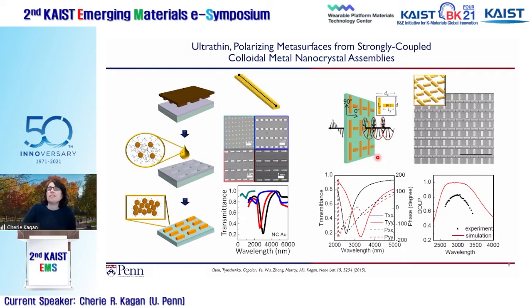So we looked at these structures and realized that we could make them and print them. You can see an example here on the right, where each of these rods is again made up of many nanocrystals, where we've done this exchange process. The rods in the X direction are slightly shorter than the rods in the Y direction. As you would expect, from simulation, if you look at the solid curve, the rods oriented in the X direction have a resonance at a shorter wavelength than the rods oriented in the Y direction, simply because we make one longer than the other.